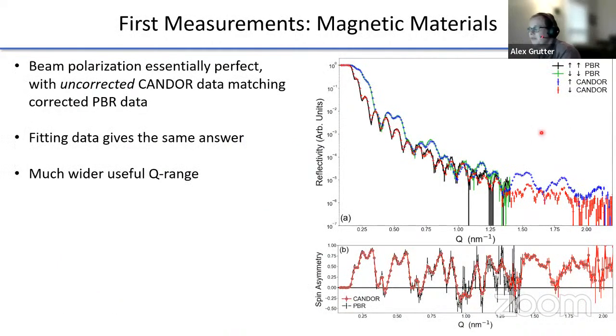And this has a really important consequence. If you look at the traditional style reflectometer error bars in the black and green, or just the black here, you see that they're quite large, right? And they get really large the higher angle you look at. On the other hand, the CANDOR error bars stay really, really tiny out to extremely high angle. And so the Q range is much wider. And I think this is really going to change how we do these sorts of measurements in the near future.